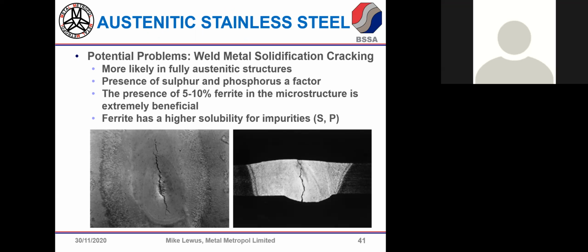One other quick thing before I jump to a couple of case studies. I might just stick with one case study because I've done rather poorly with time. Weld metal solidification cracking. It often occurs as a result of the presence of impurities like sulfur and phosphorus. Now, a key point is, particularly when we're welding austenitics, it's an advantage to choose a filler metal or conditions that give rise to a little bit of ferrite in the weld seam. The reason is the ferrite has a higher solubility for things like sulfur and phosphorus, so it acts as a kind of sink, if you like, and those deleterious elements are removed.